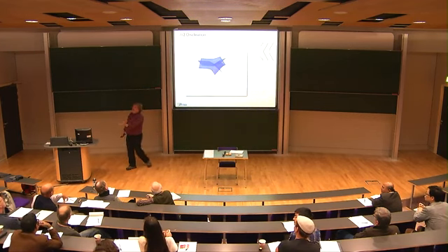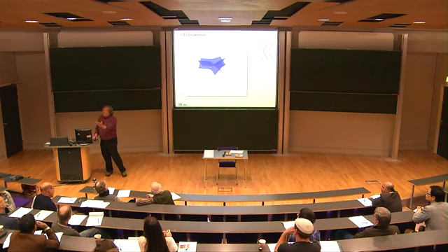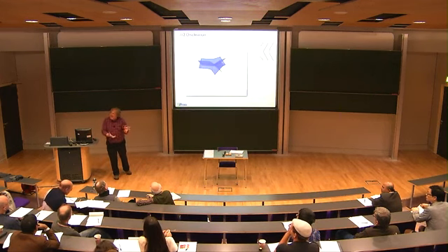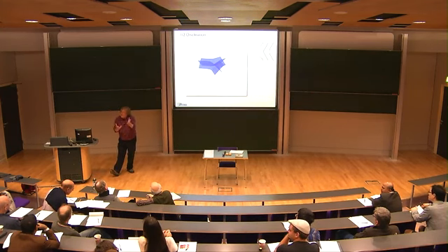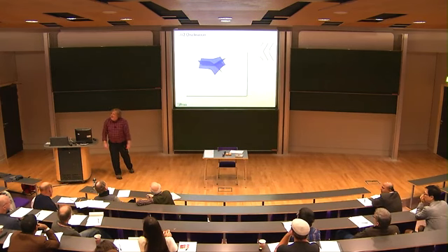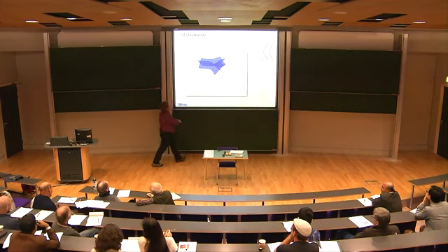Let me just add to that, if I might. As you know, Vincenzo, if I take a screw dislocation in a quadratic smectic, the energy is 0. And if I take a screw dislocation in a nonlinear smectic, the energy is infinite. So it's hard to say that the nonlinear theory is a perturbation around linear theory. I mean, you know, you could say it. Okay. Anyhow, here's the -1/2.